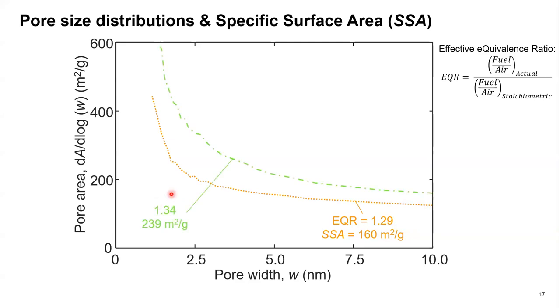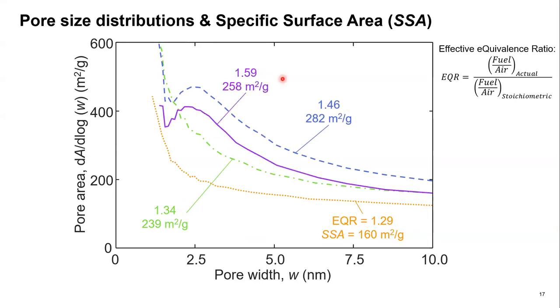At a slightly higher equivalence ratio of 1.34, the specific surface area increases to 239 meters squared per gram, and we see a very similar pore size distribution, but shifted upwards, indicating that there's a slightly higher number of pores, and this higher number of pores is what increases the specific surface area here. If we go to even higher equivalence ratios of 1.46 and also 1.59, we see specific surface areas reaching up to 282 meters squared per gram. So this appears to be due to this increase in the pores in the range of 2 to 4 nanometers, which were not present at the leaner equivalence ratios.